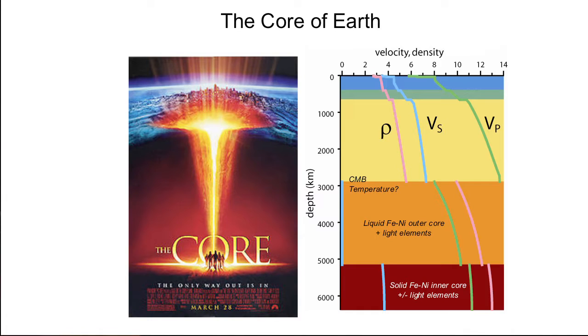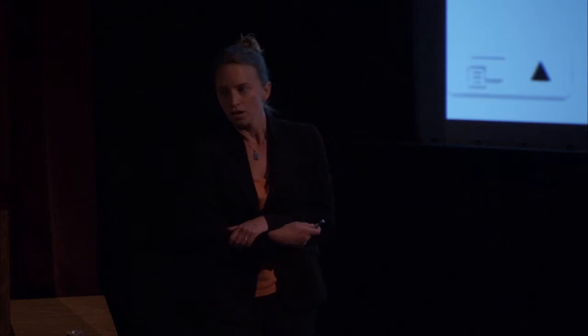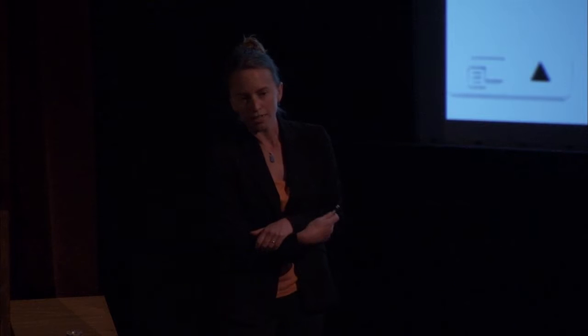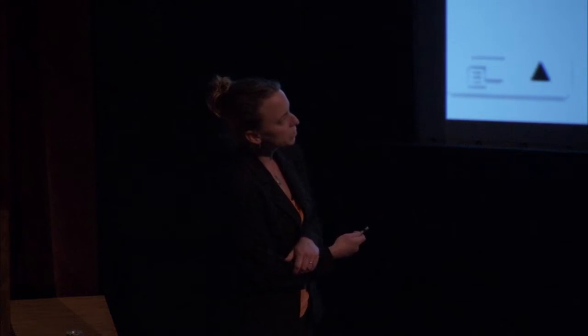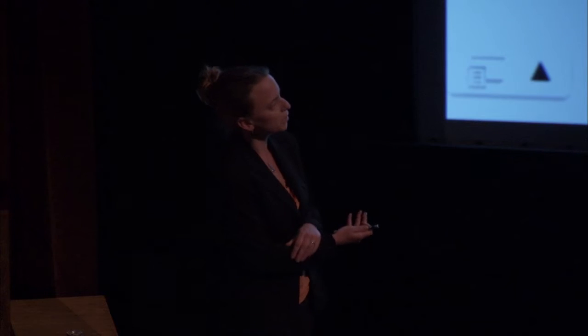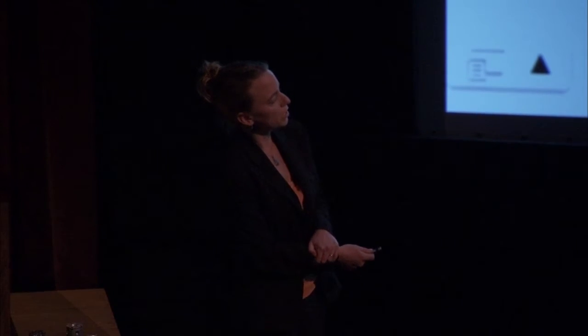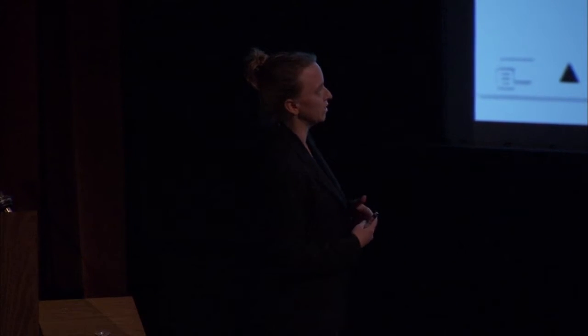Now, the reason why this is important is because this boundary, there are several reasons, but for the purpose of our discussion on these low velocity zones and the dynamics in the mantle, is that the temperature of this boundary is really not well constrained. The error estimates are about plus or minus 1,000 Kelvin, depending on current calculations and experiments. So what we would like to do is introduce a new way of determining melting and understanding how the material melts.